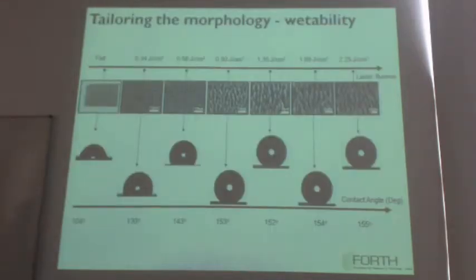Not only can we acquire this type of morphology, but we can also tune the morphology, starting from a polished, flat, smooth surface, going to the highest roughness we can produce by applying different laser parameters. For example, here is the variation of laser intensity. You can see that upon varying this intensity, one can have different micro roughness on the top of the solid surface, and also different wettabilities, different surface areas.